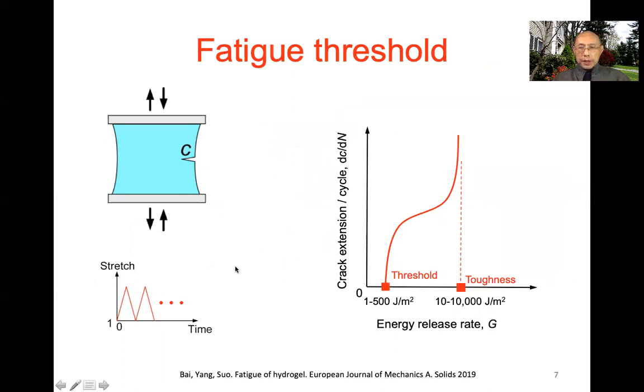So now fatigue, this is a kind of measurement many people in the field have been doing for many decades. We are also doing this. So what you do is you prepare a material, cut a crack, and apply cyclic loading. Observe crack length C growing cycle by cycle. So you plot crack extension per cycle, dC/dN, N is the number of cycles, dC is crack extension, as a function of applied load. We and other people convert the applied cyclic load to something we call energy release rate. It's standard terminology in fracture mechanics.